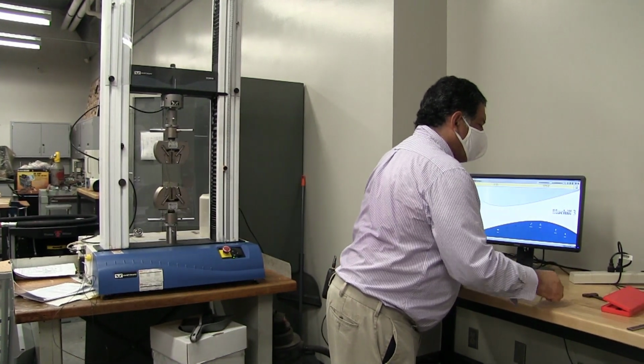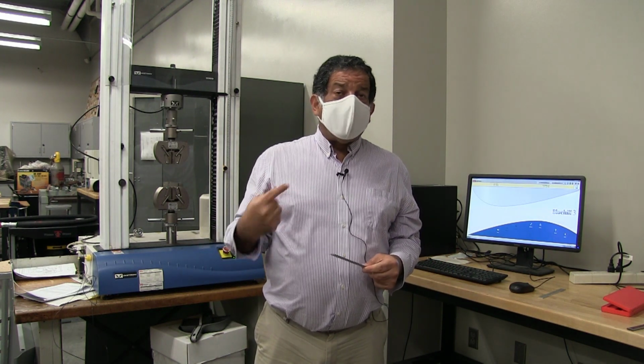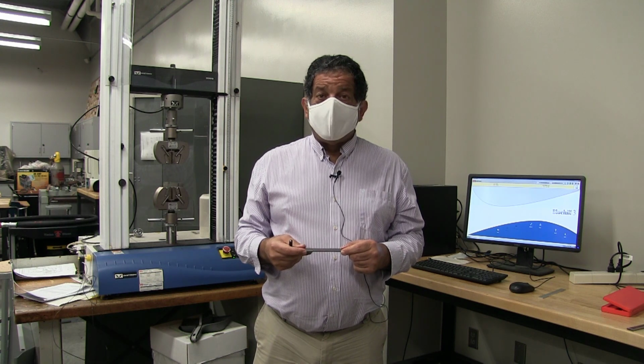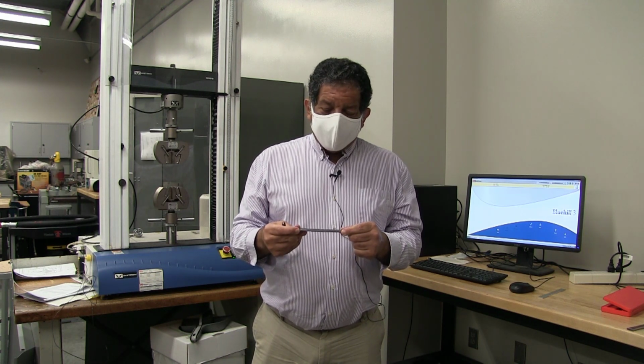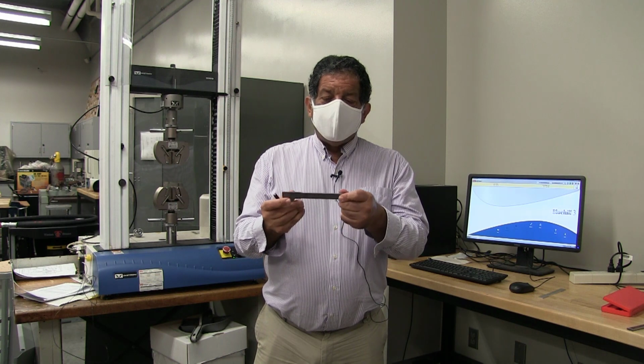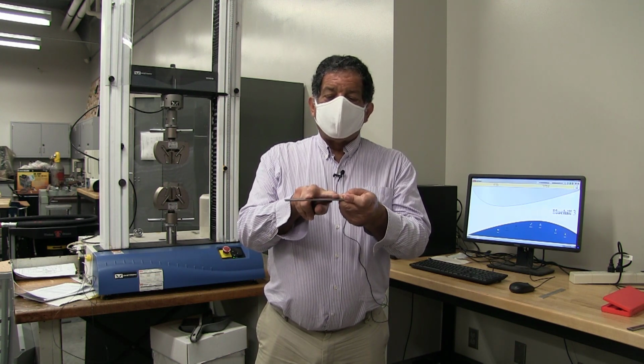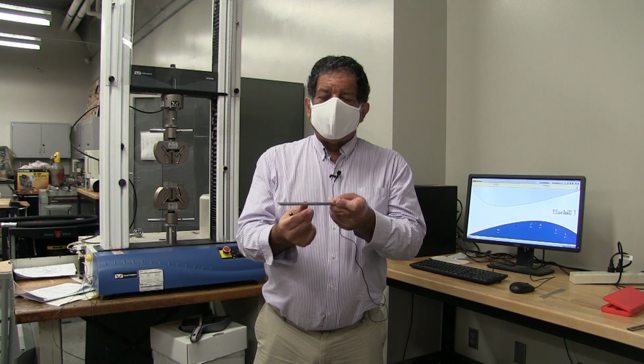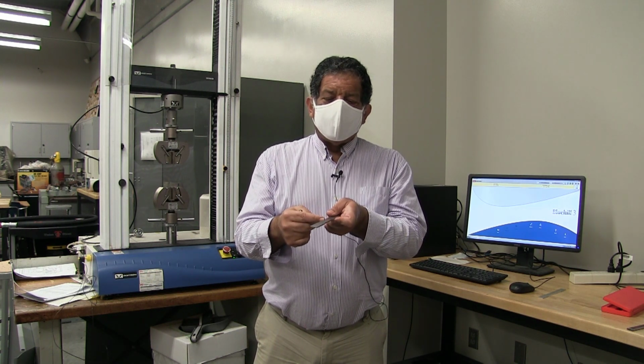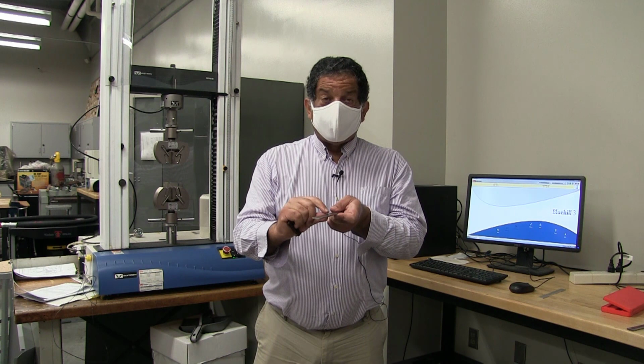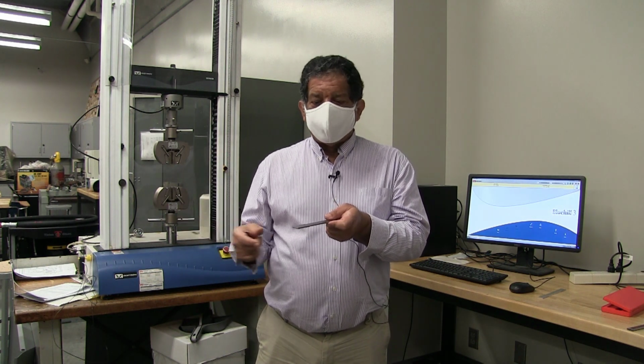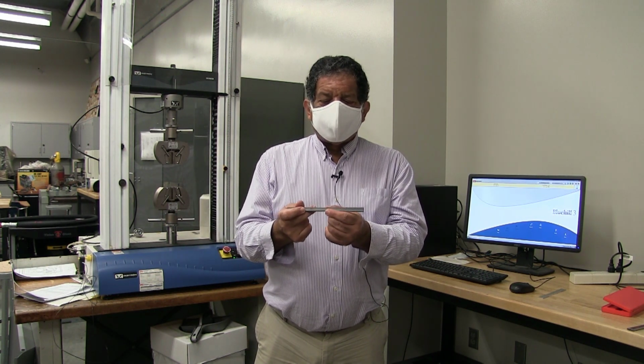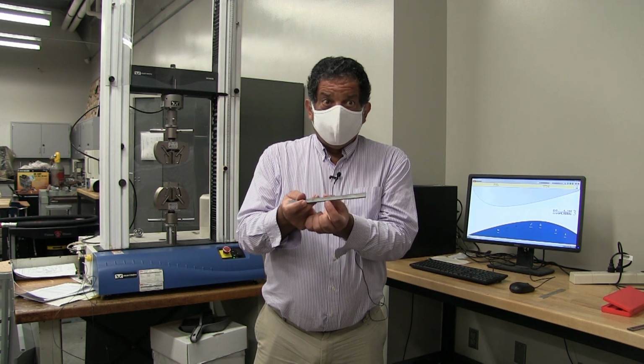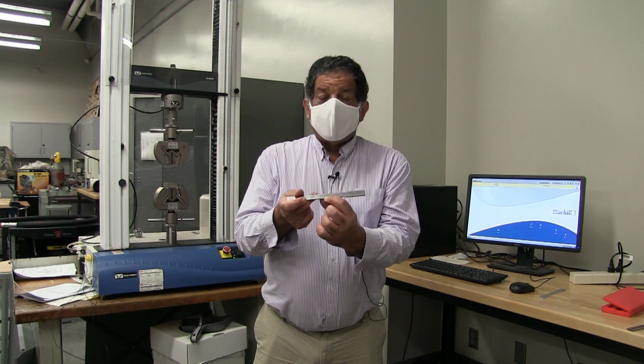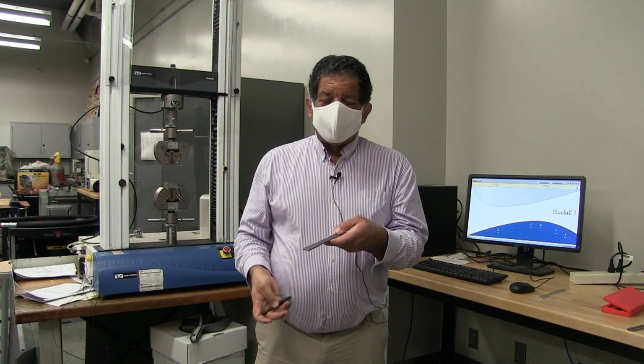For the post-processing, after your specimen breaks, you're going to want to calculate the percent elongation and percent reduction in area of the specimen. And for that, you need measurements of how much the specimen elongated relative to its original length. And then you need a measurement of the fractured cross-section of the specimen to compare to the initial cross-section of the specimen. So the fractured cross-section of the specimen, we'll have to measure the broken specimen's width and thickness, and that we will do after the specimen is fractured.